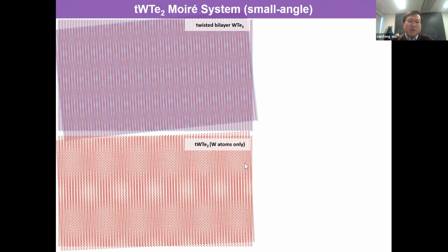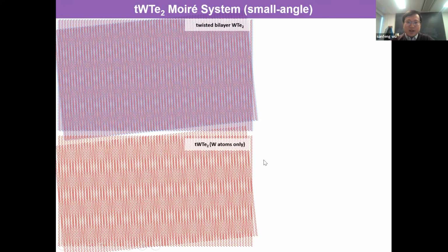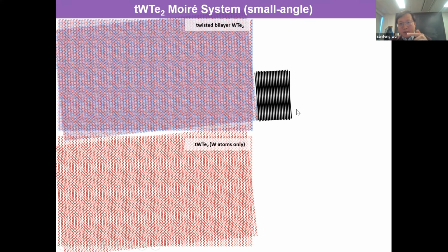On the bottom slide is the same Moiré lattice, but I only show you tungsten atoms, only to make it more clear to see. So what you see really here is, if you have a 1-dimensional chain in an array and you twist it a small angle, you have a Moiré pattern in the perpendicular direction, as I show here. So the twist angle will determine the size of the unit cell.